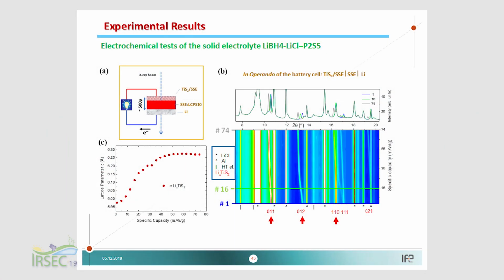The last slide is about the in situ experiment that we did, and we are happy to have managed to do this. I'm not sure if an in situ experiment of a solid-state battery exists elsewhere. We had this in transmission, which I think would not happen with other solid electrolytes without the use of these light elements, which have low scattering. And we could see a change during lithiation and delithiation.